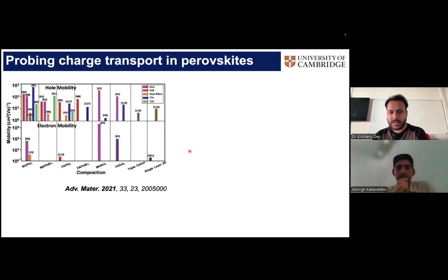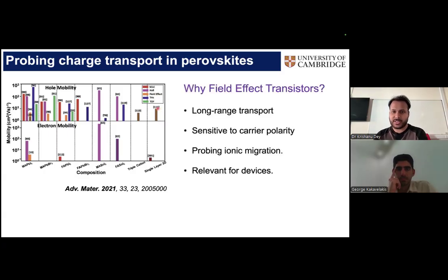And this is where I tended to use this other technique, which is the field effect transistor technique. And why I use that is because it can give you information about long-range transport, which is important for solar cells, LEDs, or any other kinds of devices where the charges need to travel longer distances. It can easily tell you whether the transport is happening through holes or electrons, so it's sensitive to the polarity of the charges. It can also probe ion migration. As I mentioned, it's a very big challenge in the field of perovskites, so this kind of technique can also give you some idea about ion migration. And all these things are relevant for devices.